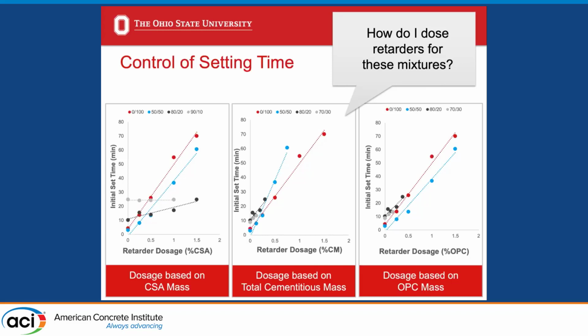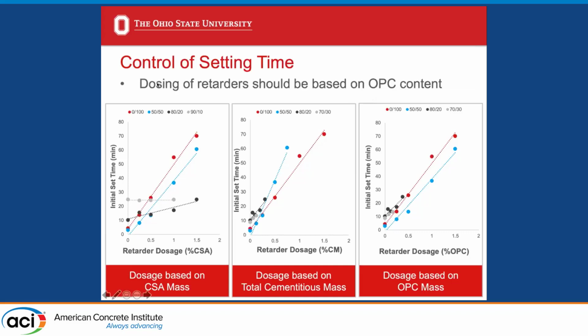And so we started out dosing our retarder based on CSA weight, and that seemed to work fine for our 100% CSA mix and for our 50-50 CSA OPC mix. But when we went to smaller percentages of CSA and larger percentages of OPC, the relationship between retarder dosage and initial set time changes radically. So we went back and tried to rethink this a little bit. And I've shown here retarder dosage based on total cementitious content relative to the initial set time. And you can see that things align a lot better when we normalize by total cementitious content. And the results are even more aligned when you normalize by just OPC mass. So we have more predictable results when we proportion retarder based on the OPC percentage rather than based on CSA mass or total cementitious content.